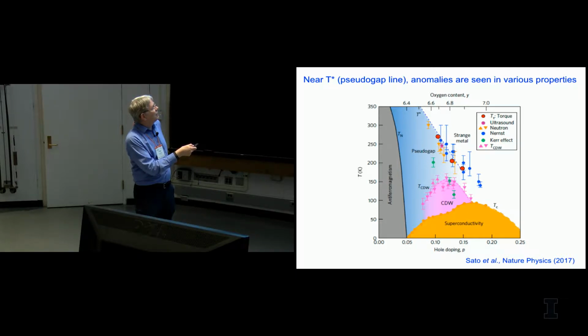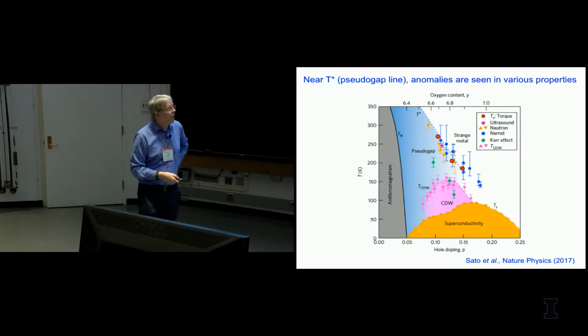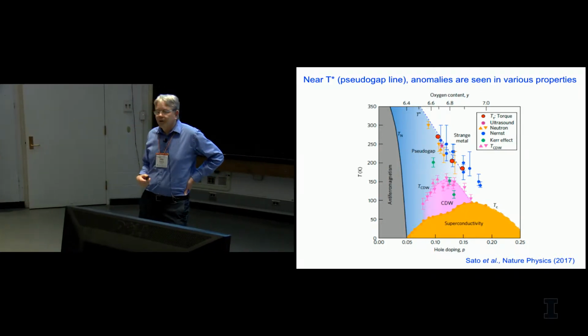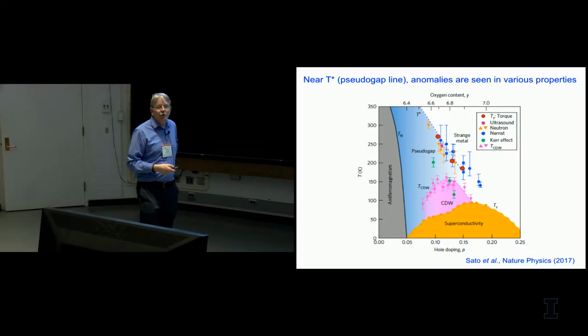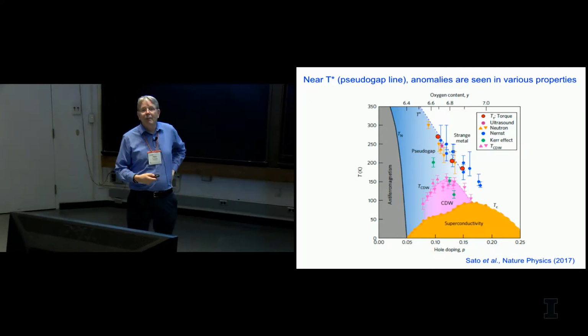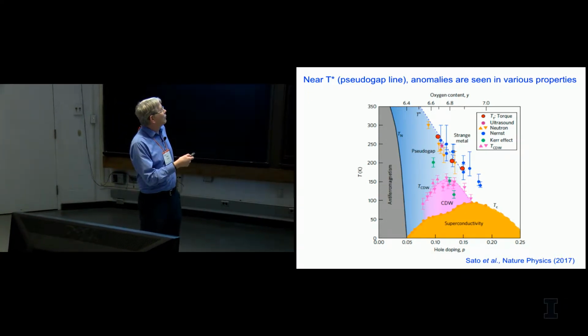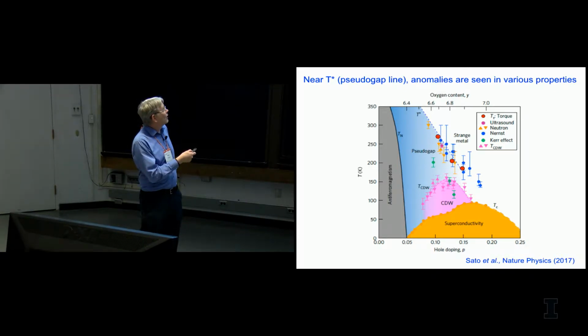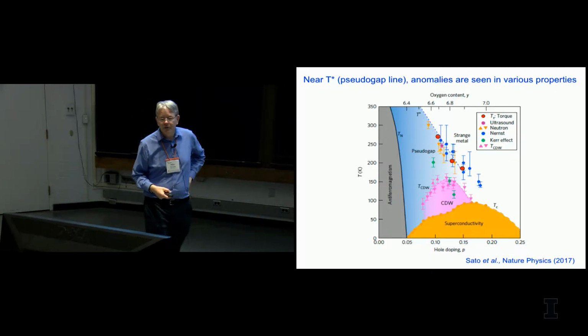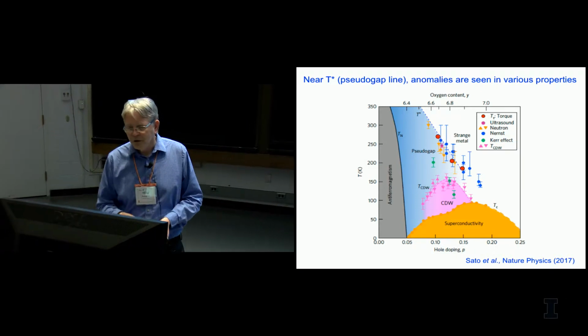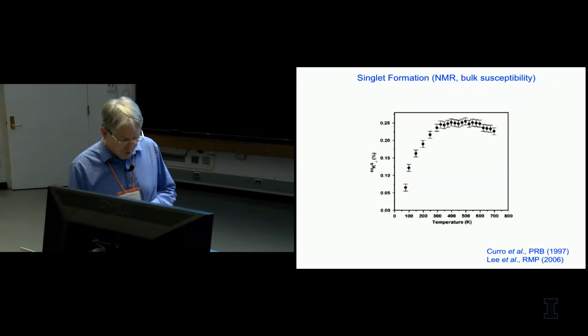And then eventually, at low doping, you have a metal insulator transition where you go from a superconducting phase to the antiferromagnet. And actually, if you look at the resistance near this boundary point, people like Dell have worked on this, you actually see the universal conductance value for pairs. So it looks like you're going from mobile Cooper pairs to localized Cooper pairs as you go across this phase point. So the pseudogap phase was known for a long time.